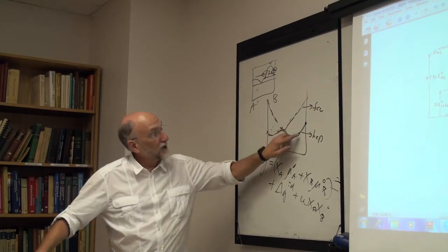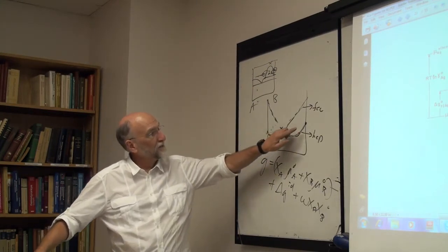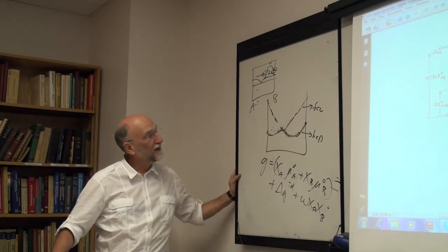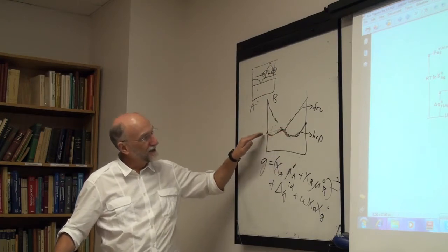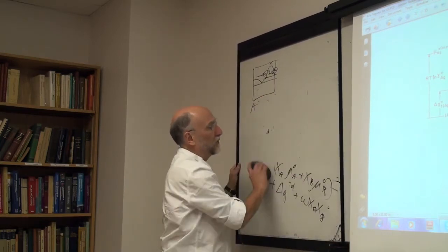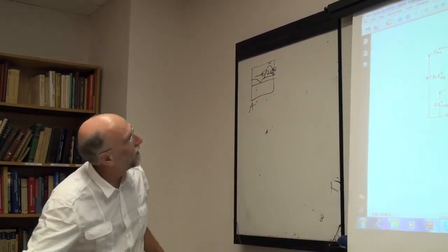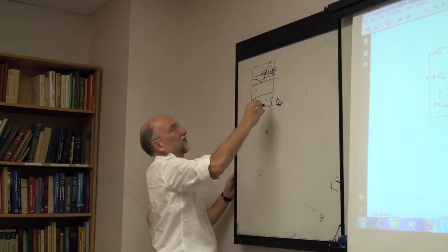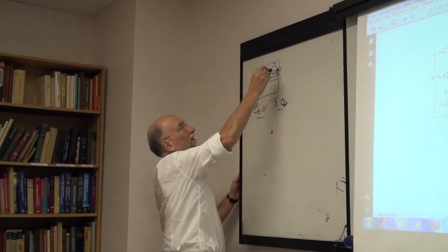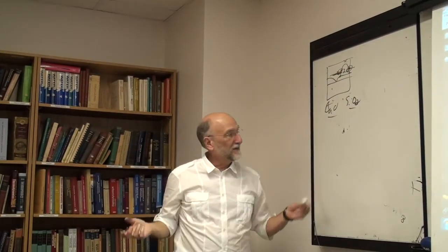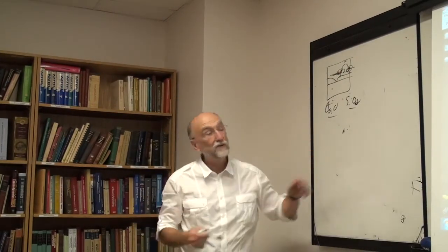You're assuming you've got the one structure over the whole region. You're assuming all the assumptions of regular solution theory apply. You're assuming kind of the same structure across the whole thing, but the structures can actually be fairly different. Even if you have a liquid, I gave the example before of, say, calcium oxide and silica. Here you have two liquids. Well, that's sort of an extreme case, but the liquid over here is ionic. The liquid over here is very different, and you don't expect the same sort of polynomial expansion to apply to the entire composition region.